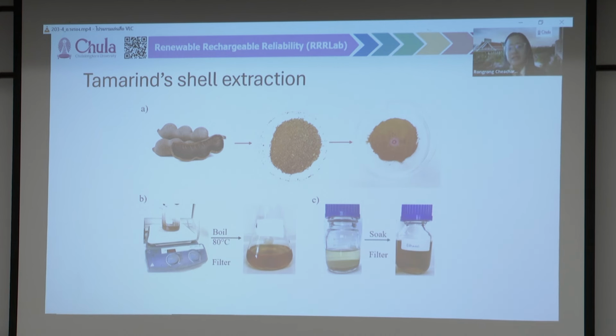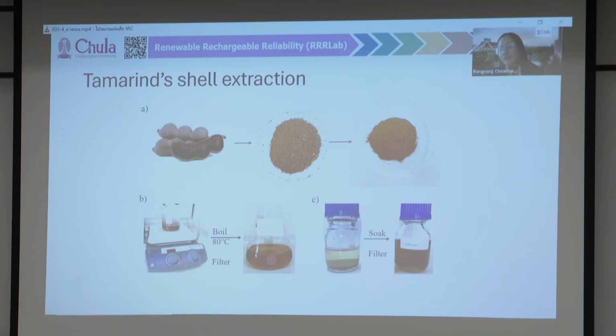we investigate two different ways to extract the organics and potassium from tamarind. One of them is water-based. In this case, we put the tamarind shell powder in a tea bag, and then we boil it or heat it up at 80 degrees Celsius for as long as you steep your tea. But in this case, we do it for less than 1 hour, maybe 10 to 30 minutes. And then after that, we filter it out, and then we use this as is.